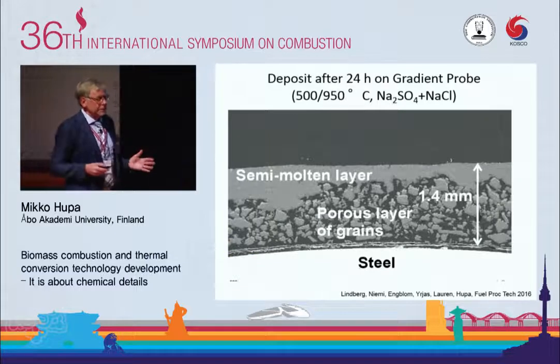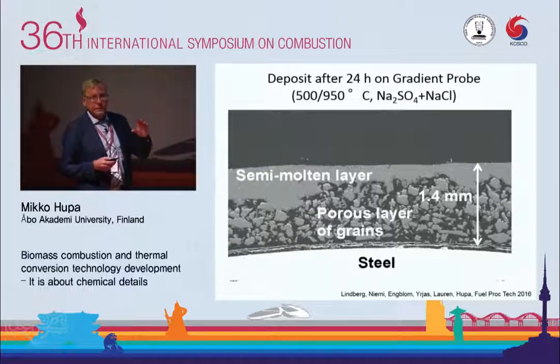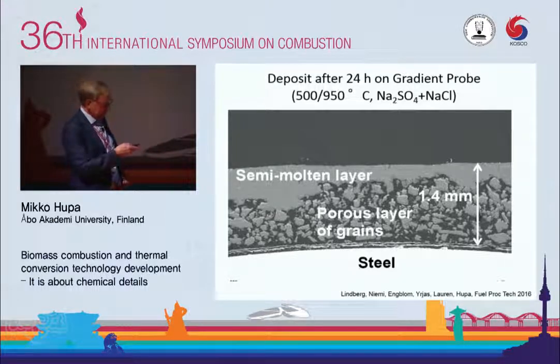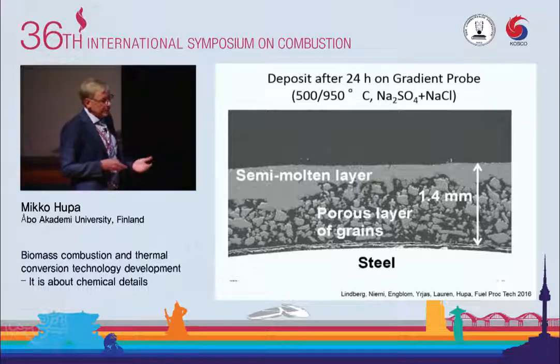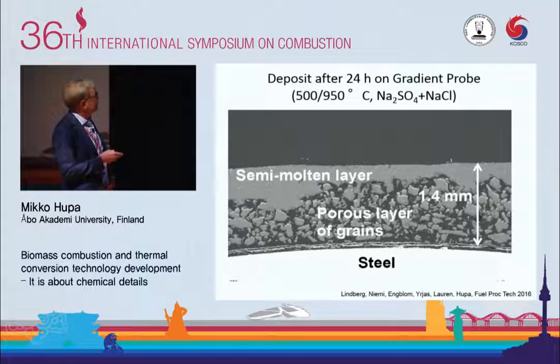And it was interesting. If we put a layer of salt on that gradient condition and let it be there one day, this is what we saw. Here is the salt deposit. This is the cooled steel. Here has been the hot environment. So instead of having homogeneous particles which look like something like this, we can see that the outer side is almost molten, semi-molten, and this is a mixture of, we used here as a model substance, sodium sulfate, sodium chloride, which is a good model because we know its melting behavior very well. So this is logical. Here we have 500 degrees, and then somewhere here this system starts melting at 730. So somewhere here we have had a temperature of 730.